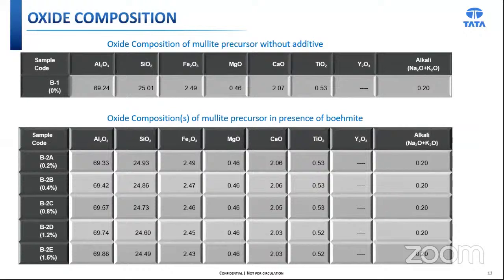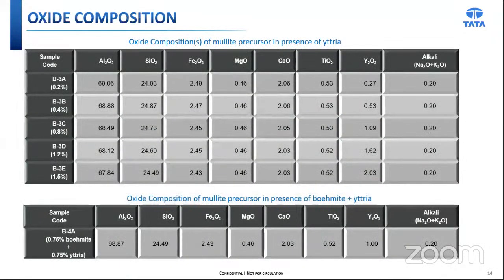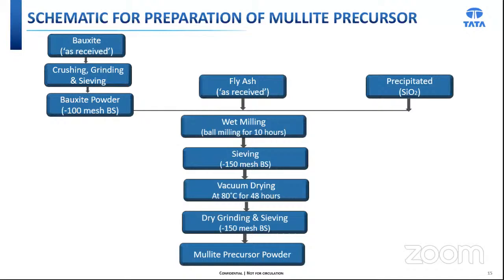These are the oxide compositions derived from the mullite precursor without additive, in the presence of boehmite, in the presence of yttria, and with the combined additive. This is the schematic for preparation of the mullite precursor. Now this is the procedure for how the precursor powder has been produced.